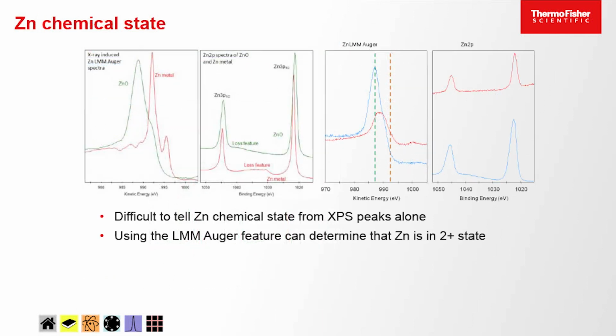So once we've identified the elements present, we'll collect high-resolution scans. And so I've got some here for, these are the reference data from the knowledge viewer for zinc. This is one of those Auger features I was talking about. This is the core level for zinc. That's a typo, that should say 2p, not 3p. And then over here we have, from the sample, we have the zinc Auger and the core level.